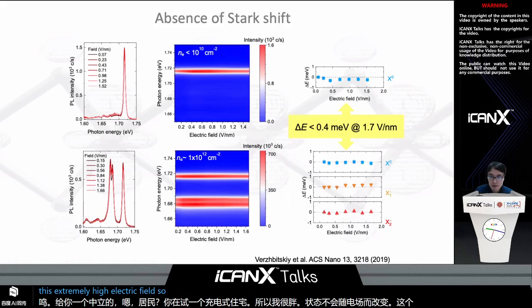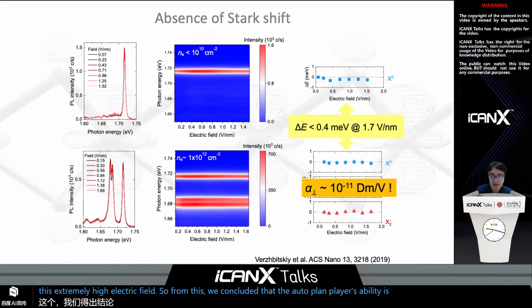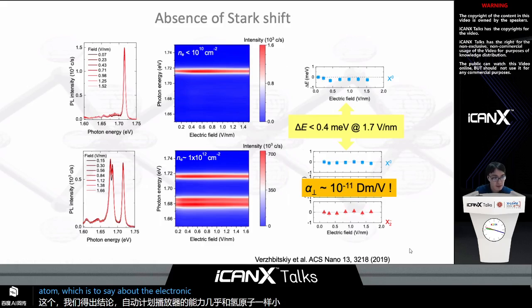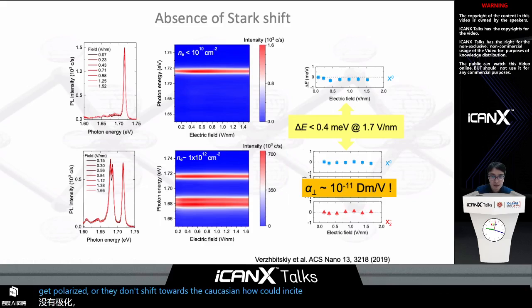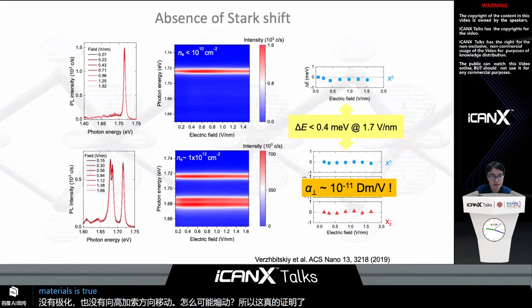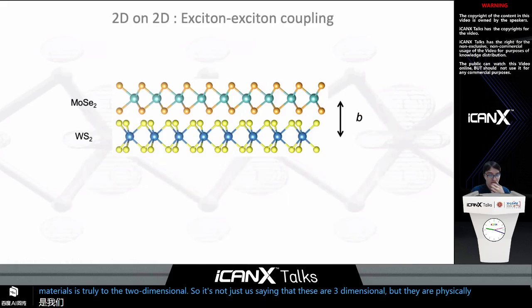So from this, we concluded that the out-of-plane polarizability is almost as small as that of a hydrogen atom, which is to say that the electron-hole pairs, or the excitons, are strongly bound to the metal sites, and they don't get polarized, or they don't shift towards the chalcogen sites. So this really proves that the excitons in our 2D materials are truly two-dimensional. It's not just us saying that these are two-dimensional, but they are physically two-dimensional.